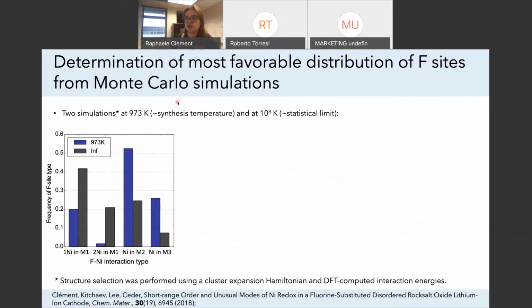So here we did two simulations, one at the synthesis temperature of these materials around 1,000 Kelvin, and one at very high temperature to mimic the statistical limits. And what we're comparing here is the distribution of fluorine environments under these two conditions. So one is the random distribution of cation species, and this is for the distribution that we expect in our material. So here is a plot showing the frequency of different types of fluorine sites in this material that have been categorized as a function of their interaction with nickel.